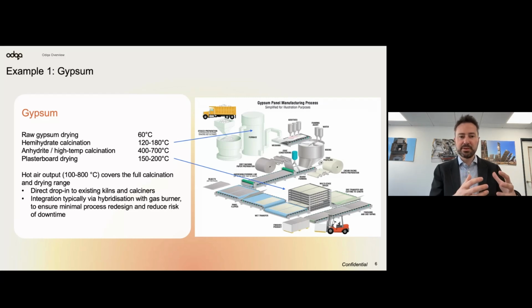You take the raw gypsum from the ground, which you need to dry ahead of doing anything else at relatively low temperatures. Then there's a calcination step, which is at a higher set of temperatures, which is done in a furnace. Very straightforward to bring hot air into that rather than burning fossil fuels. Then there's a process to take those elements, bring them through, create and roll the plasterboard, and then once the plasterboard has been created, again, it needs to be dried before it's then shipped to the end consumer.